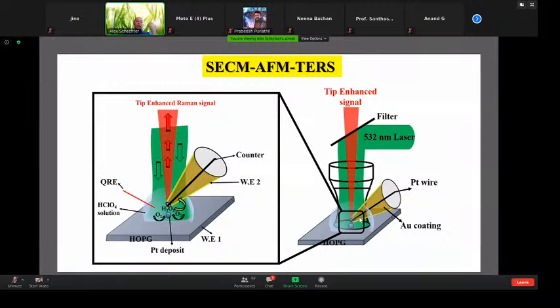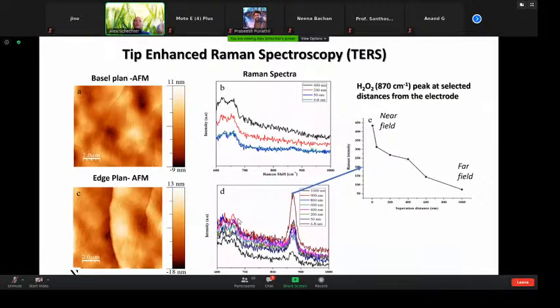So the gold acts as a plasmon enhancer, and so what we have here is an enhancement of the Raman signal. Or in other words, we can detect the Raman signal or the absorption right under the tip of the AFM, the gold tip. So here's what we get. You can look at this, this is just looking at plain carbon, no defects, nothing. And we can see that we have no significant peaks at different distances. Even as we go towards the surface, we have no peak of peroxide.